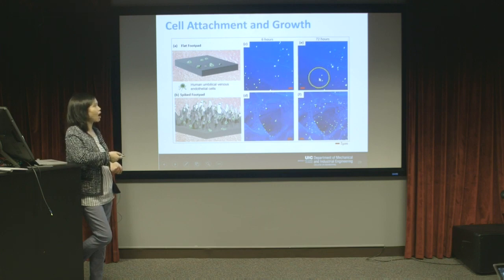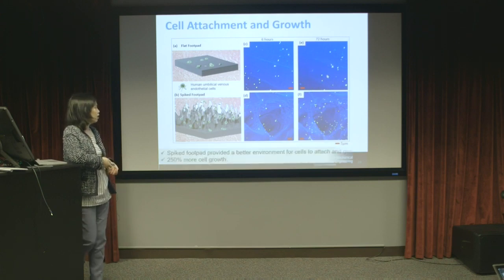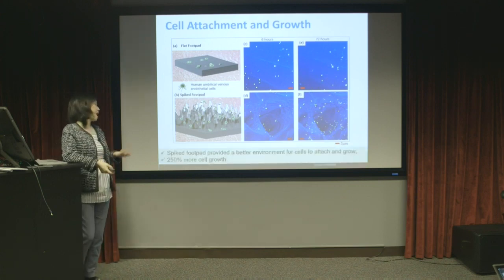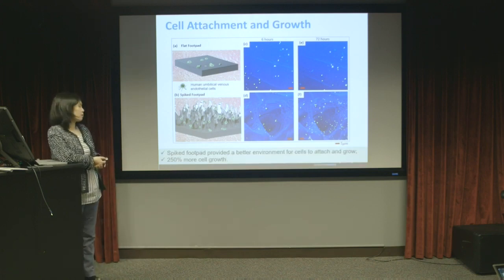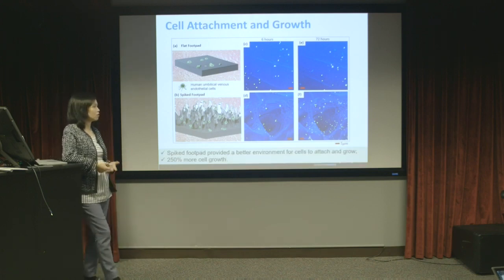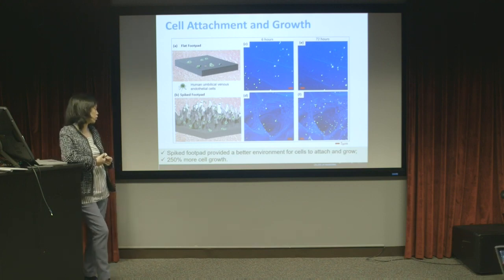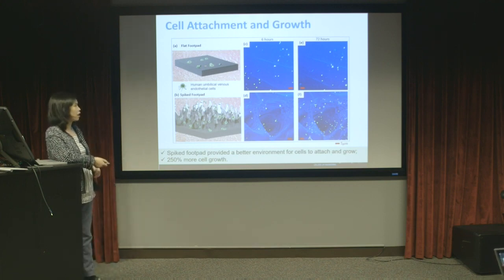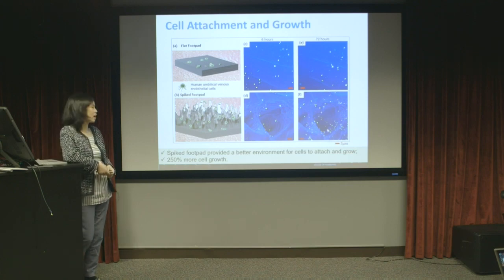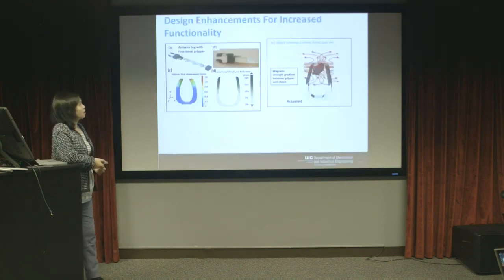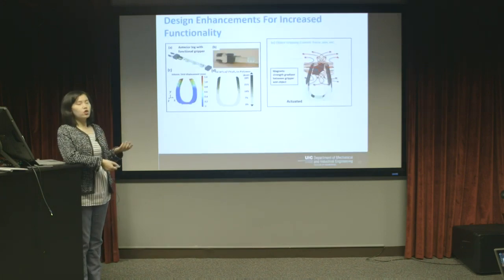And after 72 hours, you can see that the spiked footpad surface has much more cells than the flat surface. So we conclude that the multiple scale spiked footpad provided a much better environment for cells to attach and to grow. And we did some quantitative analysis and found that the spiked footpad has about 250% more cell growth on it.